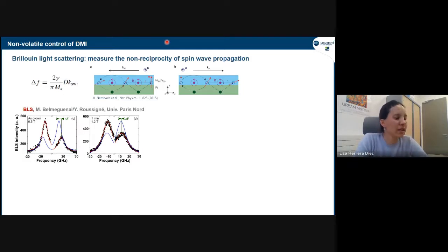And then one way to evaluate and get the values of the DMI is Brillouin light scattering. One other important thing about DMI is that it's chiral. It imposes a chirality on the system. That means that the spins winding in, let's say, a clockwise direction is not the same as winding in the anti-clockwise direction. This will be given by the sign of the DMI. This can be probed if the propagation of spin waves is measured. A spin wave propagating in one direction with the spins winding, let's say, in the clockwise direction, will not be the same as propagating in the opposite direction. This is really what you measure. There will be a shift in the frequency of these spin waves, and this is related to the DMI. This is what we measure with the Brillouin light scattering. And then this allows us to get the parameter and the sign of the DMI.